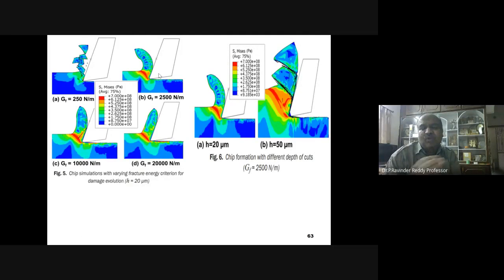When the chip is flowing and you wanted to see the strain energy release rate, so energy, what we can calculate at different locations. When your chip is curling, there is going to be a separation, break, connecting at certain points. And here you have a continuous form. So if you see the lower energy, it's breaking and discontinuous. And at the higher energy level, you have continuity, so plastic deformation, and it is going to be very continuous. But high values at this place, high energy values.